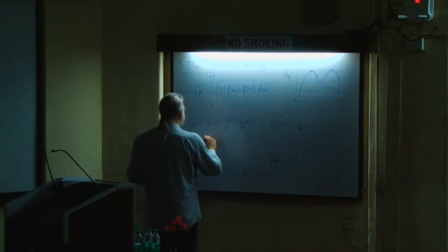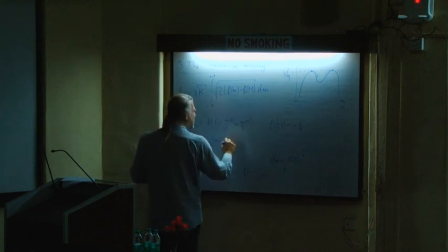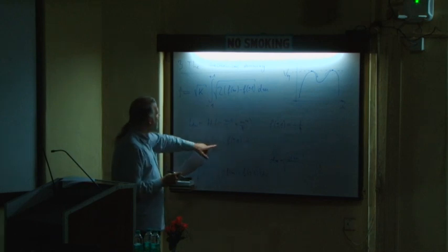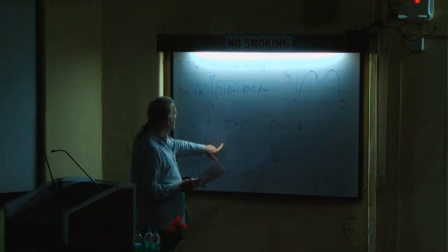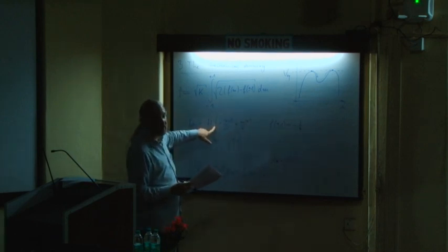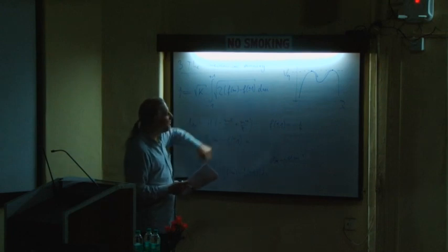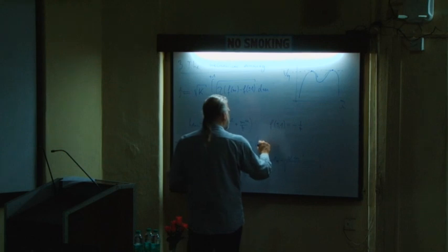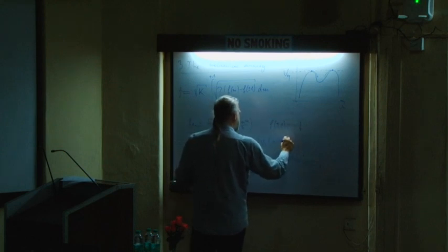So that means if I form f double well of m minus f of plus or minus 1, you see if I subtract minus 1/4, this gives you a plus 1/4 here. And you see that this is a perfect square. So this will give you 1/4 times (1 minus m squared) squared.